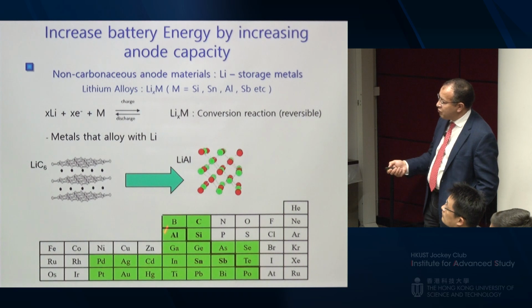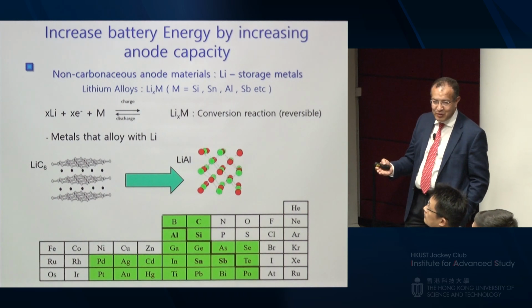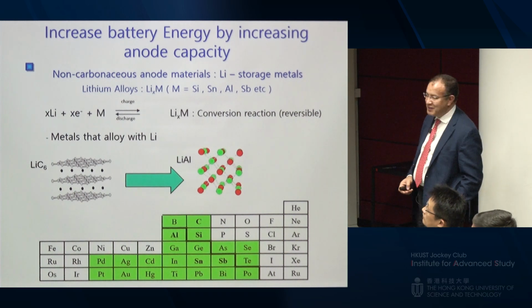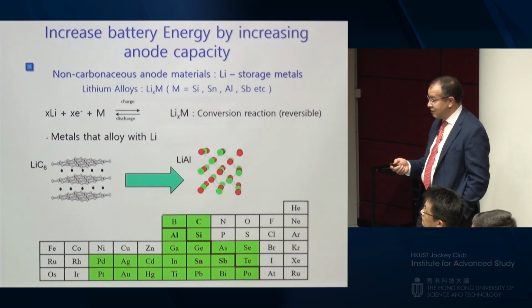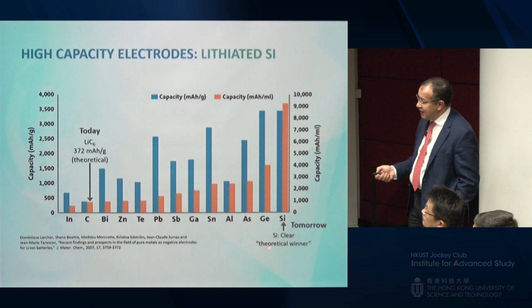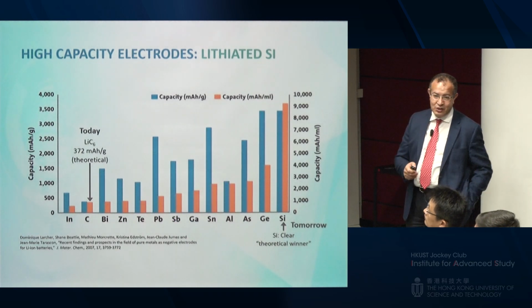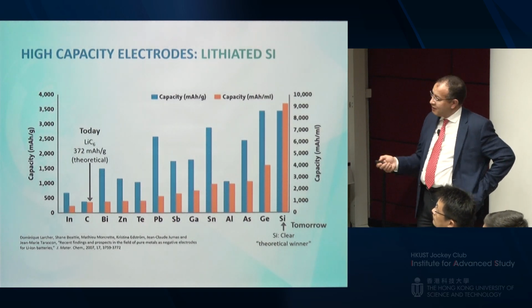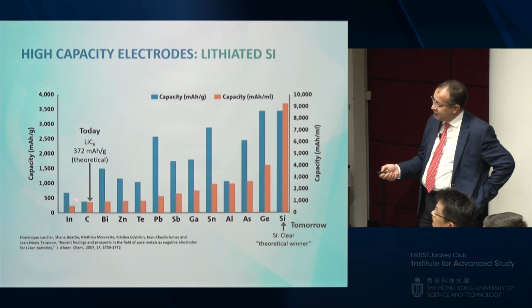You have a whole bunch of metals that you can alloy lithium with. And obviously, silicon is the most attractive because it's dirt cheap. You have plenty of it in the earth. And it also gives you the higher volumetric and gravimetric energy density than other metals. It's almost 10 times graphite.